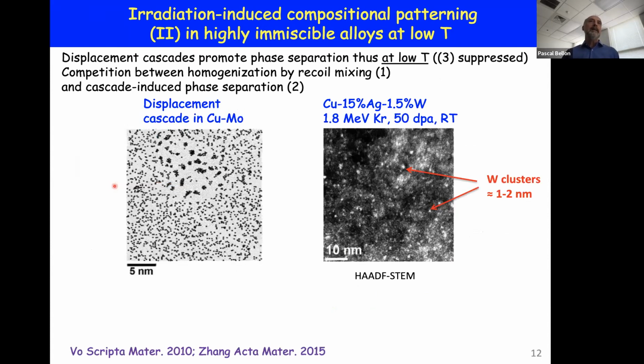There's another type of self-organization that can also happen, if we take alloy systems that are highly immiscible, such as copper molybdenum, copper tungsten. The displacement cascade is such that we can think of it as a very hot liquid for a picosecond or two. If you look at the equilibrium phase diagram of the copper molybdenum system, these two elements are even immiscible in the liquid state. And so what's happening here is that in that displacement cascade, molybdenum clustering starts to take place. This is a snapshot of a molecular dynamics simulation.